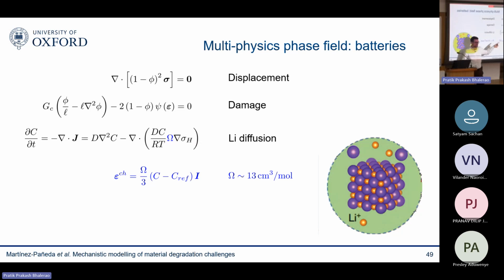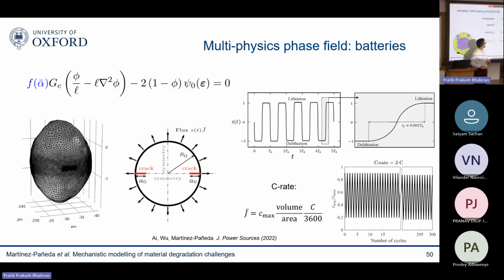And this is the main point. We have these chemical strains. In fact, in these batteries, we're not applying mechanical load. It's just the charge and discharge, the lithium ions coming in and out, that are causing the swelling and the shrinking of those particles through those chemical strains. So you can capture that in the model.